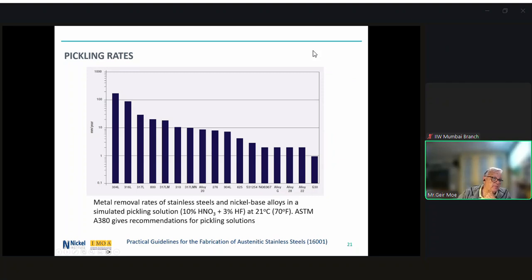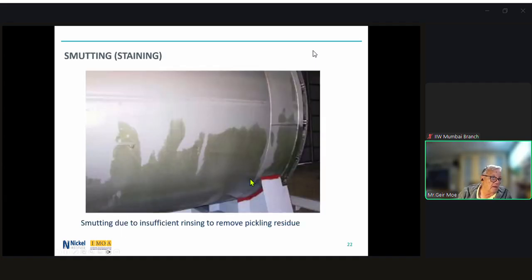But material should be pre-cleaned to remove oil and grease which may mask the surface. After pickling, the component must be thoroughly rinsed with clean low chloride water. Otherwise, smutting may occur, which is due to the presence of all of these metallic elements drying out onto the surface.